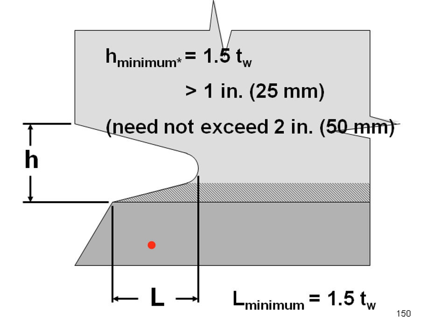Now you see the dimensions here where the height, h, needs to be 1.5 T sub W, not less than 1 inch, and doesn't need to exceed 2 inches. The width here is 1.5 T sub W, T sub W, of course, being the thickness of the web.